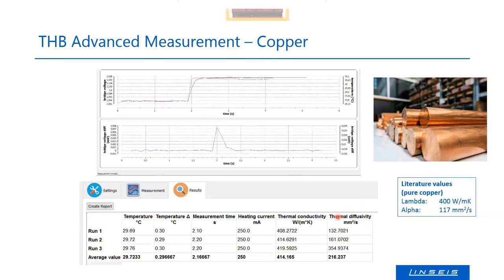For the thermal diffusivity, we are a bit off, because now we are, with this advanced instrument, already above the limit, above the time resolution. With the THB Ultimate, it would be possible to measure thermal diffusivities also for copper with an accuracy of 5 to 10%.